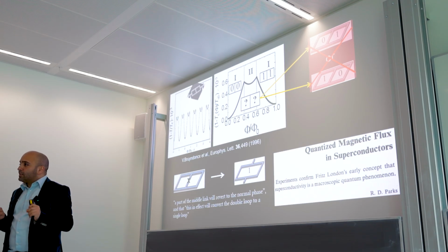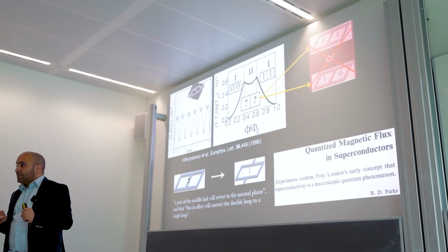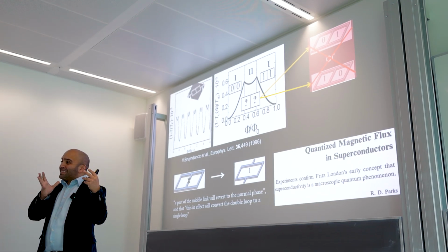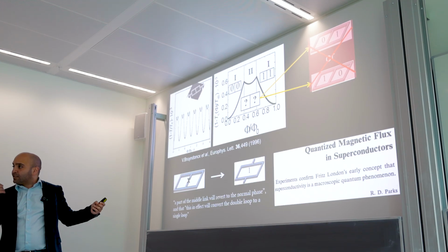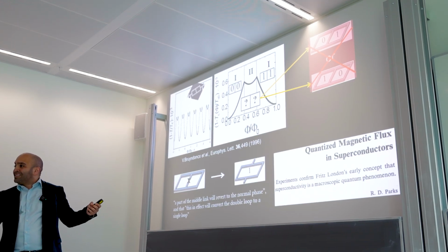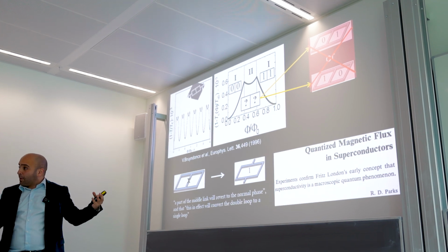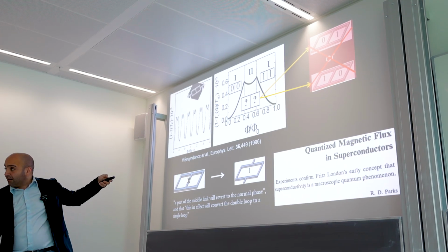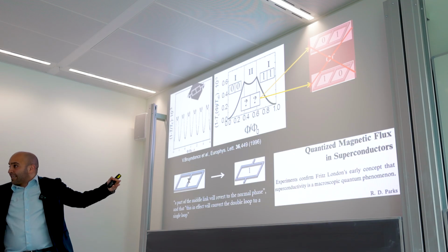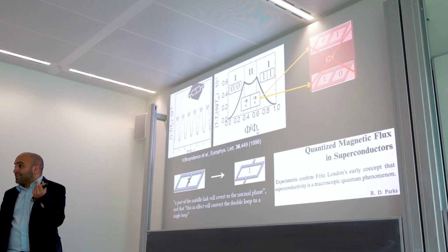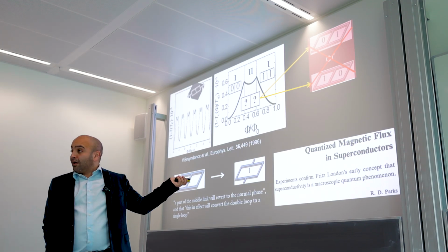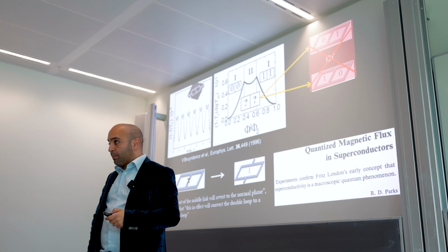It's normal, but that doesn't always mean that there are no Cooper pairs. Basically what happens is that you have incoherent Cooper pairs. You have a vortex constantly crossing this line and disrupting the phase coherence. This is called phase slip. So, in this case, even if you have Cooper pairs, if you do a shot noise experiment where you can see Cooper pairs, it gives you a measure of 2e, but it would still be incoherent. We'll come back to incoherent Cooper pairs later, of course.